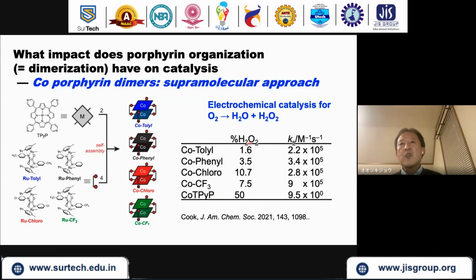This is a monomer. H2O2 percent is 50%, so random production of H2O and H2O2. But upon dimerization, the percent hydrogen peroxide reduces dramatically, meaning that they are more selective towards water, and the reaction rate increases dramatically. For the monomer it is 9 times 10 to the 0th per this unit, but the dimer has about 10 to the 4th or 10 to the 5th times faster reaction by using these dimer structures. So this is a recent work, and this is still a very topical subject.